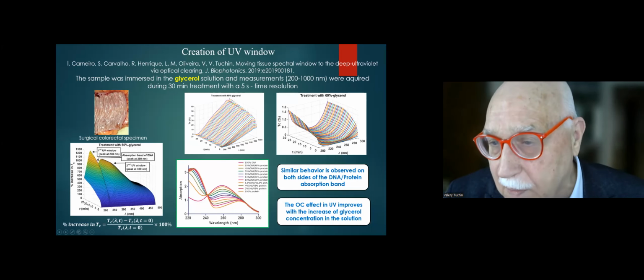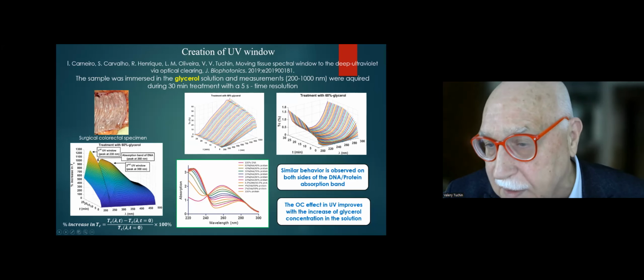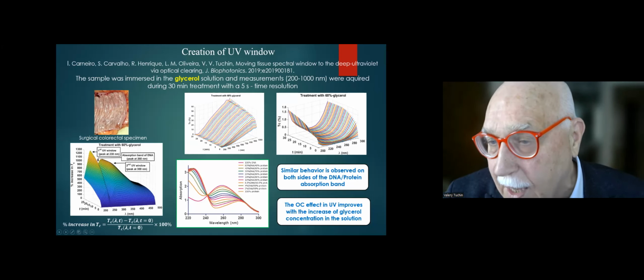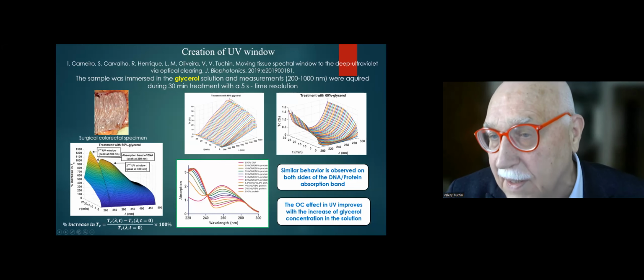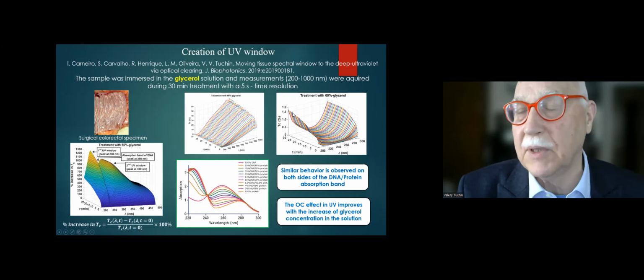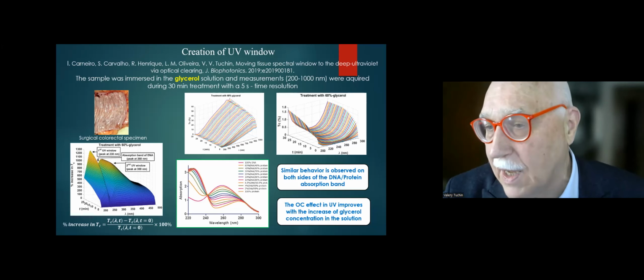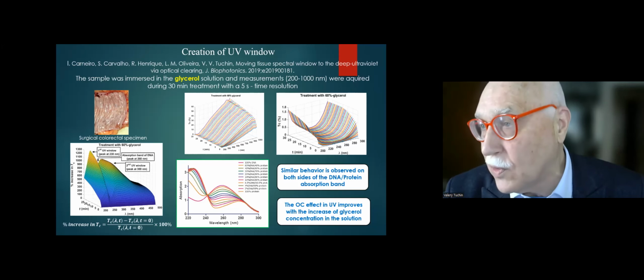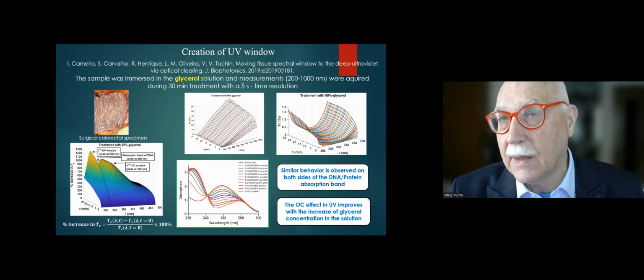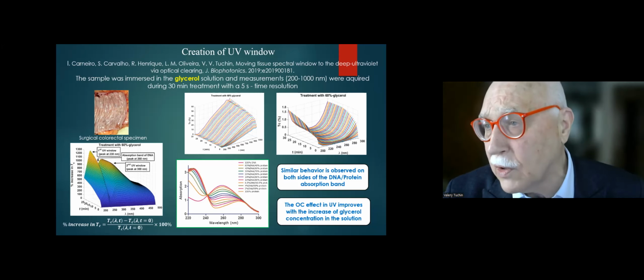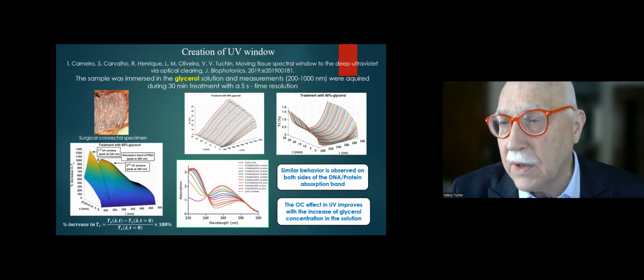But please pay attention to this graph. You see here, this is the 0 time, this is 30 minutes, and this is collimated transmittance in the ultraviolet. This is 200 nanometers. Indeed, collimated transmittance is very small. But after optical clearing, we can increase it up to 20 times. So indeed, we have a huge number of photons, which is enough to use any technology, imaging technology or spectroscopy technology, which are using the